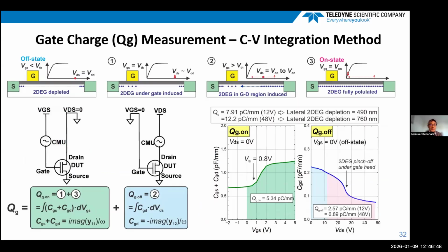Here it shows how we extract the gate charge of such devices. On the top, I show how the transistor 2-DEG is accumulated when the transistor is switched from off state to on state. And we use the CV integration method to extract the gate charge. We measure CGS plus CGD as a function of VGS at on state, and we measure CGD at off state as a function of drain voltage. By integrating those CV characteristics, we obtained QG.